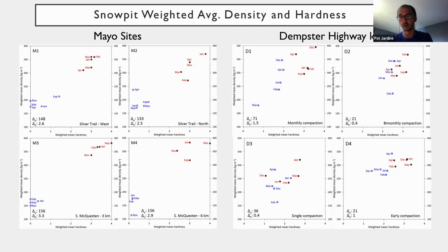Properties were multiplied by the proportion of the snow pit that the layer they were measured in took up, and then all the layers were added together. The blue circles show the undisturbed sites, while the red are compacted, and the month the snow pit was dug is indicated beside the circles. In Mayo, the natural snowpack consistently had a density of about 150 to 200 kilograms per cubic meter, and hardness is near 0 or 1. After compaction, the hardness rose to about 3, while the density rose to about 350.